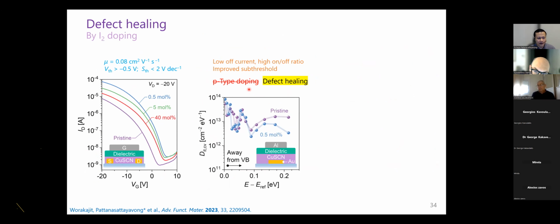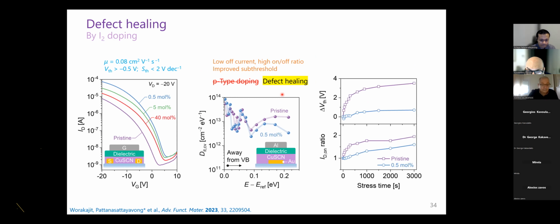So adding iodine inside, from this work, we see that it's actually not a p-type doping, but a defect passivation effect. Okay, so it's a defect passivation. We also observe that other device characteristics become better, like the threshold voltage and also the on-off ratio, and also quite stable compared to the non-treated.